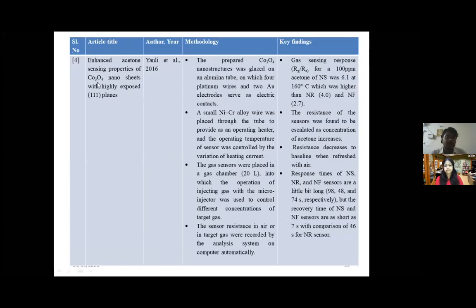The fourth one is the cobalt oxide nanostructured chemiresistive material. Here they studied 100 ppm with a response of 6.1 at 160 degrees Celsius. They explored which morphology, that is, which structure of this nanomaterial, would provide a higher response. They studied nanosheet, nanorod, and nanofiber, and found that the nanosheet provides a better response. They attribute this to the surface to volume ratio. The sheet is a 2D material, compared to the nanorod and nanofiber, which are 1D materials. Hence the nanosheet has a high surface to volume ratio. They reduced the temperature, but with an increase in response and recovery time. So we need to take care of the working temperature and the response and recovery time.